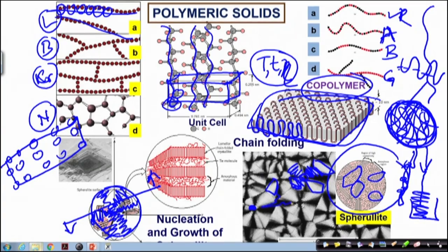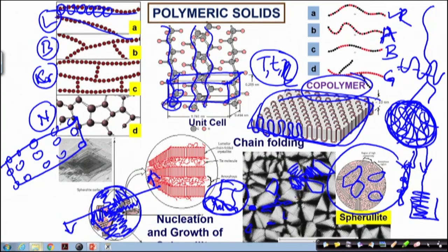In between we also have dark regions, and these dark regions are non-crystalline regions. If you compare this with a metal — in a metal or a completely crystalline ceramic — you will find 99 percent of the bulk as crystal, and only 1 or 2 percent of the area will be grain boundaries or phase boundaries, which are non-crystalline regions. Whereas in a polymeric crystal, at best you can have about 70 to 90 percent which are crystalline, but in-between regions will be non-crystalline. The boundary regions are much more extensive simply because each of these chains also has a certain amount of rigidity, so it is not always possible to make 100 percent crystalline crystal from such chains.